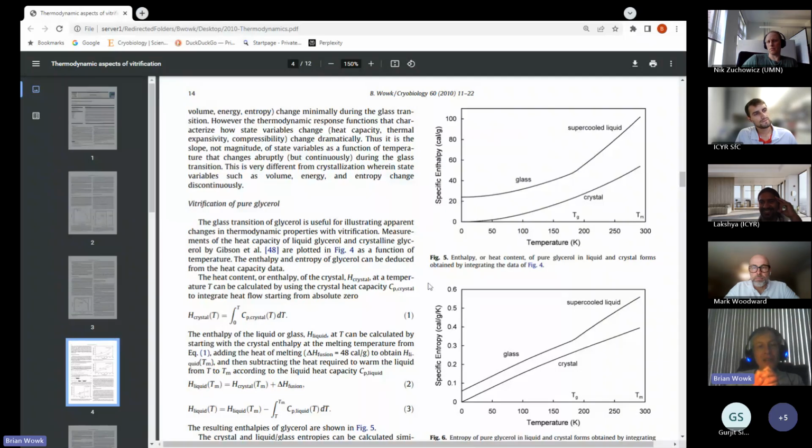And the reason we rarely see solidified glycerol is because it has a strong tendency to supercool. So you could usually even put it in the refrigerator and it won't freeze. It takes a lot to nucleate it, but the actual technical temperature at which pure glycerol crystallizes, or crystallization is thermodynamically favored, is plus 18 degrees Celsius.